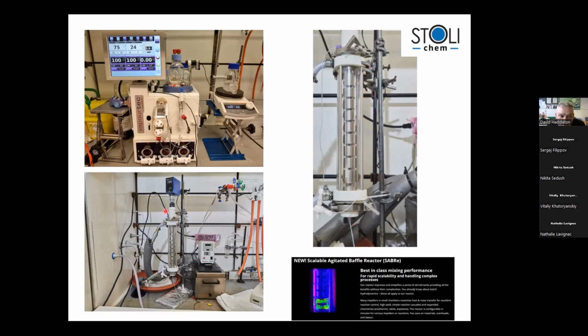So all of these stir with the overhead stirrer at the same rate, but as we push it through, it goes into this one, stirs for a bit, and then to the next one, into the next one, into the next one, and this really improves the mixing as opposed to plug flow going down a single tube. I haven't got time to do a lecture on that, but the improved mixing, especially in free radical polymerization and catalytic chain transfer polymerization, will give us a narrower dispersity. So we do that in flow.